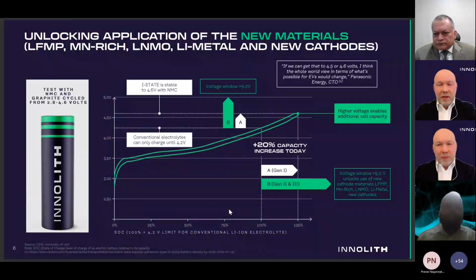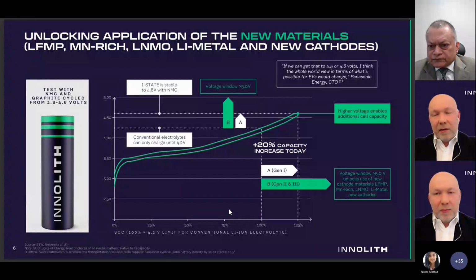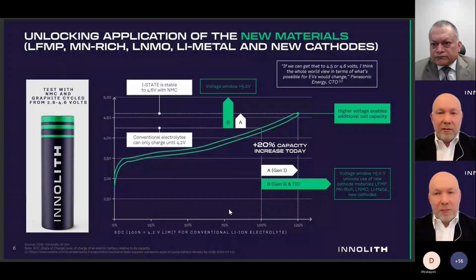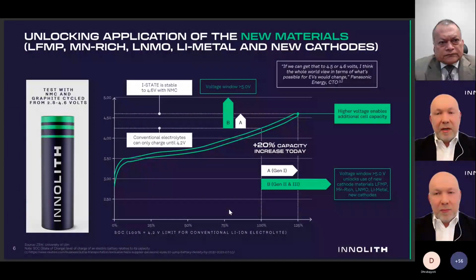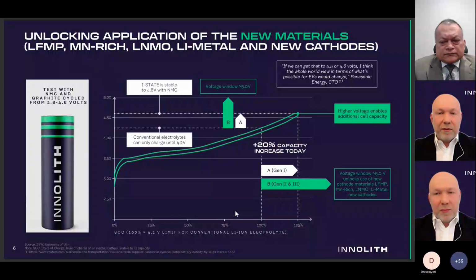So, for example, with NMC 811, we usually go to 4.6, and this is what is shown with arrow A. Going from 4.2 up to 4.6 volts, and then continuing along the charge and discharge curve, you can see on the x-axis that we get additional capacity of 20 to 25%. This is exactly thanks to high voltage stability. With high voltage stability, we can utilize almost 100% of the lithium inside the cathode material. Using this full potential of the cathode material, we increase the capacity of the cell, and for the same capacity, we reduce the quantity of cathode in a cell.